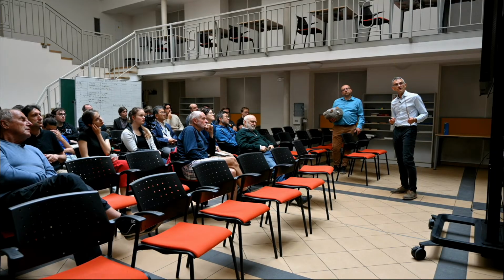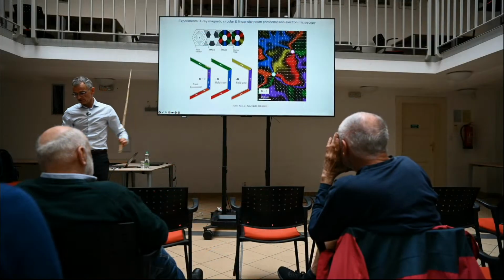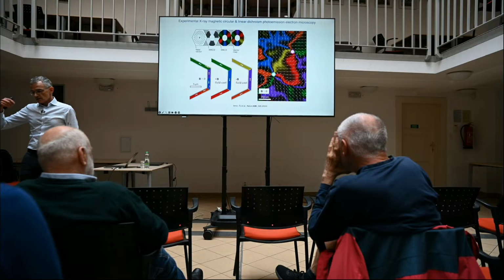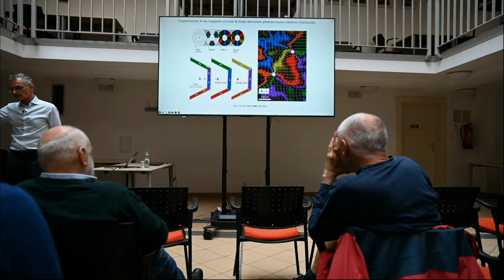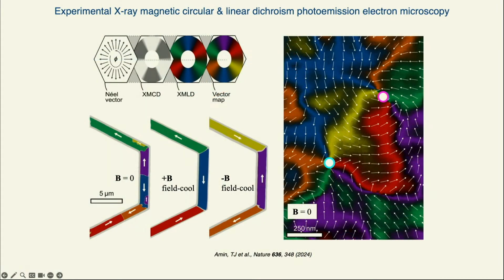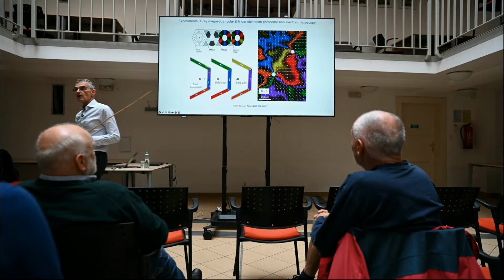So this has been already demonstrated, and these images, by the way, are direct microscopy images of the Néel vector done by photoemission electron microscopy combined with various X-ray dichroisms, in particular the circular dichroism, which is something that people thought, again, was only possible in ferromagnets, but in altermagnets we can have circular dichroism or anomalous Hall effect, these time reversal symmetry breaking effects, equally well. What is imaged here is the axis, but also the sign, of the Néel vector in the altermagnet. And to the best of my knowledge, these are the first microscopy images of real space imaging of the full vector map of a Néel vector in any compensated magnet.